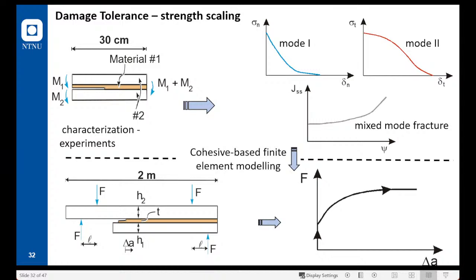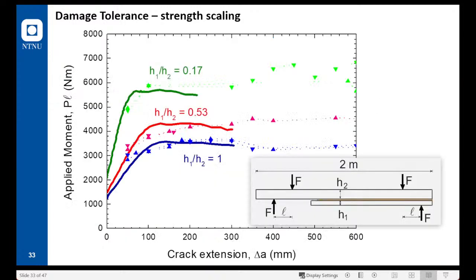In practice, we do experiments at the macro scale. You can see the length of the specimen here. We extract the cohesive laws for different mode mixities, and we model the behavior of the specimen. And we can see that we can predict quite well the behavior of the 2 meter beam from data from the different lower scales. So we see how the cohesive law can be transferred across the different length scales.